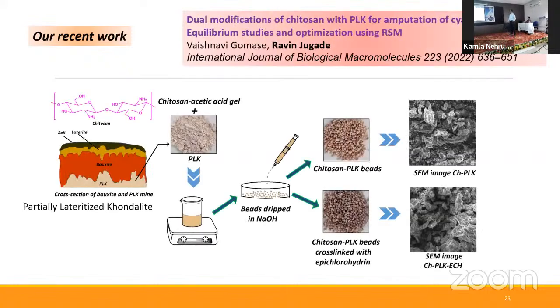Recently, what we have done is we have carried out modifications of chitosan in various ways. The PLK, a partially lateritized khondalite, coming from the ore of alumina, was clubbed with chitosan, forming the beads in two ways. One, chitosan PLK beads, and chitosan PLK beads cross-linked with epichlorohydrin.